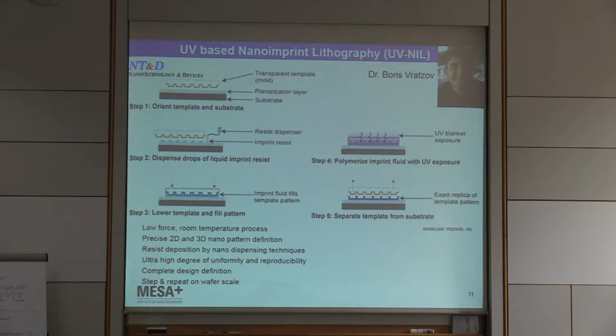How many times can you use the template before it wears out? Yeah, so I think it's on the order of a few hundred times or so. It depends a little bit on how well you pamper the templates and clean them, and if there are impurities on your substrate, you may induce defects on it. So you really have to pamper them. But as far as I understand, you can use them a couple of hundred times or so.